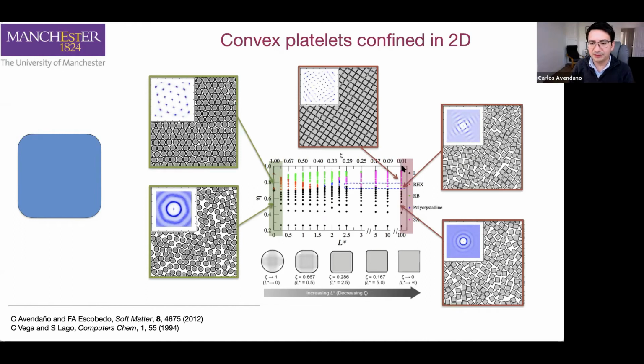At high densities, we observe the formation of the square phase, where you can see that the structure factor, or the Fourier transform of the density distribution, gives you the perfect peaks in the lattice. And in between, we observe the formation of that tetratic phase that I was talking about before, where you can still see the square symmetry, but the rings, or the peaks, are not very defined. They are actually diffuse, telling you that the correlations decay very quickly in space. So we had the two extremes completely characterized. Now we are in the position to study what happens in between.